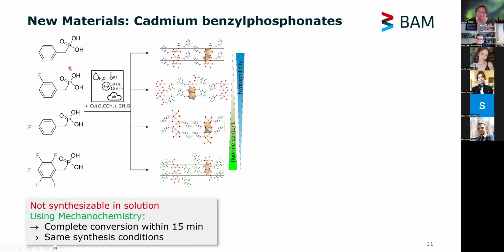It turned out, for instance here, these materials, we were interested in with a different degree of fluorination. They were not so easy to synthesize in solution, or not at all possible to synthesize them in solution. But it turns out that you can just make them super easily, just providing the linker and then here, cadmium acetate as a salt. And then at room temperature, within 15 minutes, you get your crystal structure.